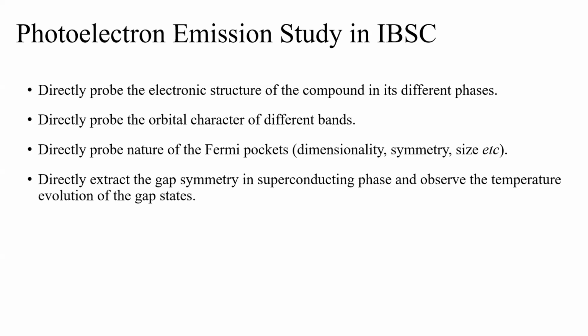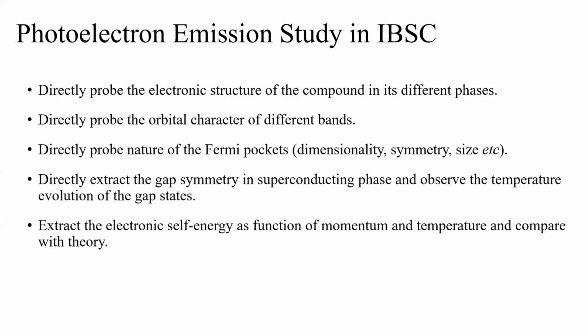You can also measure the gap symmetry. So you basically do the kx-ky plane mapping, and from there you can find the superconducting gap symmetry. Gap symmetry in these superconducting compounds is a very important parameter. Using this technique, people actually confirmed that copper-based compounds have d-wave type of symmetry, and in this case, it is s-wave type of symmetry. You can also observe the temperature evolution of the gap states, I mean, how the gaps are closing at different k values for different bands.